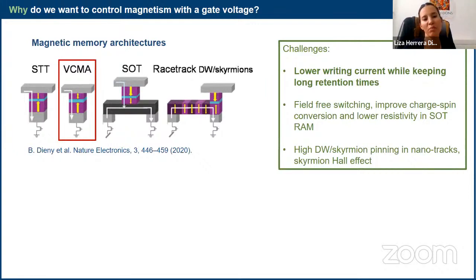But in general, one of the important points, in line with everything that we know, is one of the most important social problems that we're having, which is reducing energy consumption. That is an important point for any of these prototypes. So this is really where electrical control of magnetism can make a difference. We want lower writing currents for these magnetic memories, but at the same time, we don't want to lose robustness of the magnetic state. So we don't want to reduce, for example, anisotropy to be able to switch it better, and in the end have a memory that does not really stand temperature fluctuations.